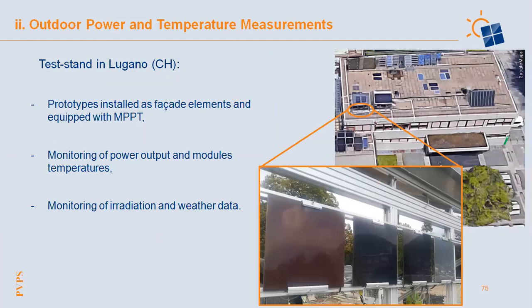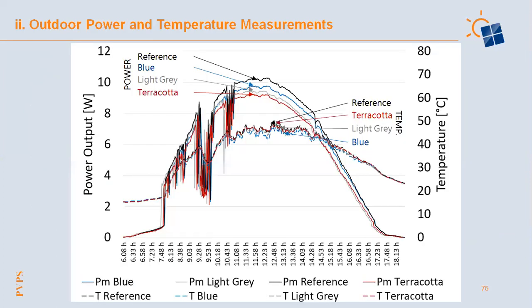However, another important aspect to investigate was the possible temperature effect of applying the color on the modules. Indeed, when the temperature of the module increases, the power output decreases. So to investigate this aspect, we set up an outdoor stand where we installed some of these prototypes as facade elements, so in the vertical position, and we equipped them with a special MPPT for monitoring these small modules. And from the results, it arises that the possible temperature effect due to the application of color on the modules is not so high and significant.